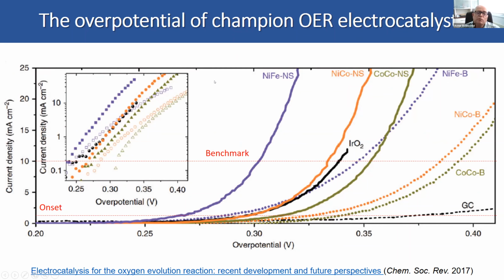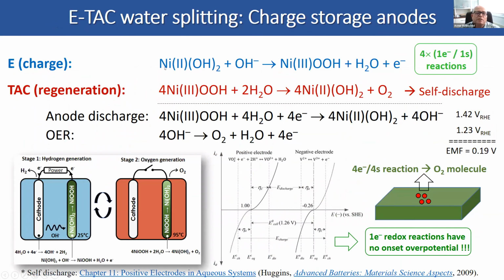So we do it differently. We do it in two stages. In the first stage, we charge nickel 2 to nickel 3. So we charge nickel hydroxide to nickel oxyhydroxide, where essentially we have to charge 4 sites in order to generate, in the next step, 1 oxygen. So instead of 4 electrons per 1 site, now we have 1 electron per 1 site reaction. And then in the second stage, which does not consume any electricity because it is a spontaneous chemical reaction, we